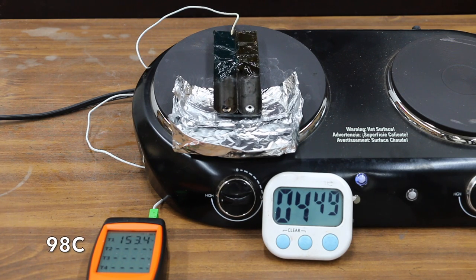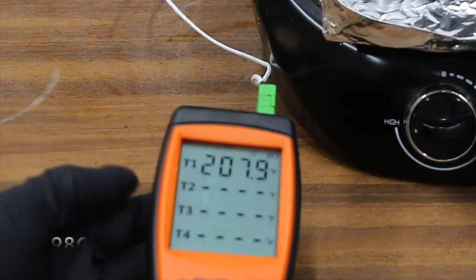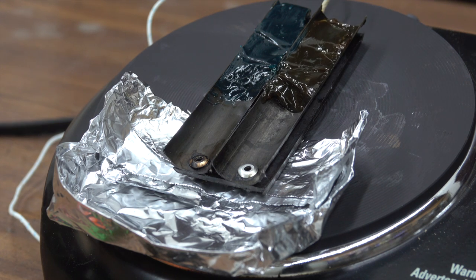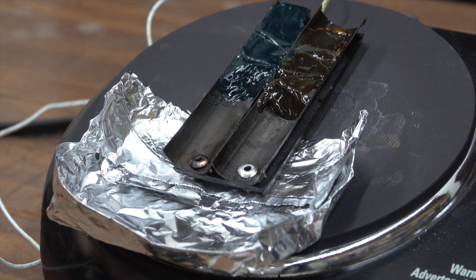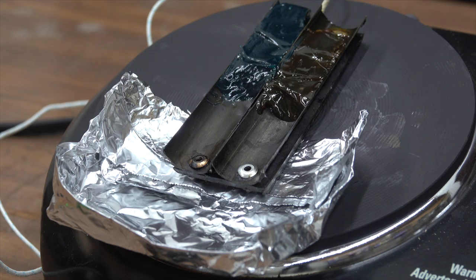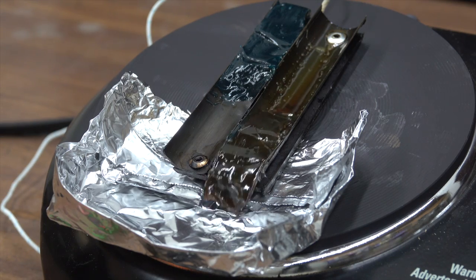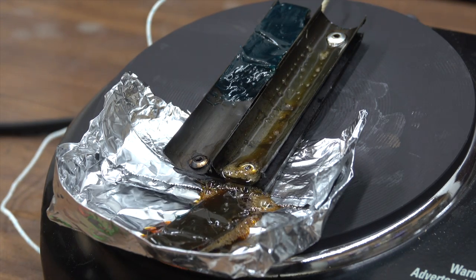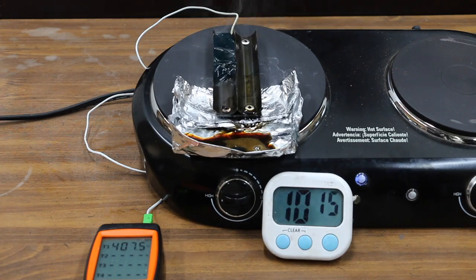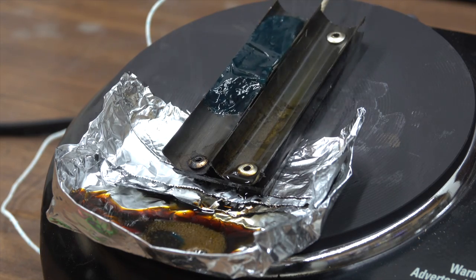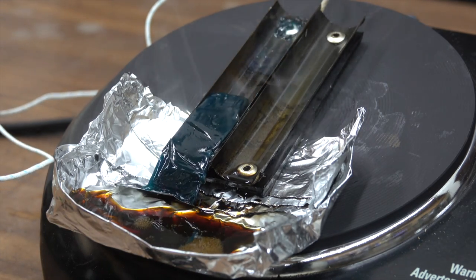It's been right at 6 minutes and the grease tester is right at 200 degrees Fahrenheit. And the vintage grease is beginning to move. Can Mag 1 hold on, or will the vintage Conoco go up in smoke first? Wow, the vintage grease does not like the heat, and it is the first to go up in smoke. And the grease tester is right at 400 degrees Fahrenheit, and the Mag 1 is starting to head down the slide. So it's the Mag 1 grease for the win.